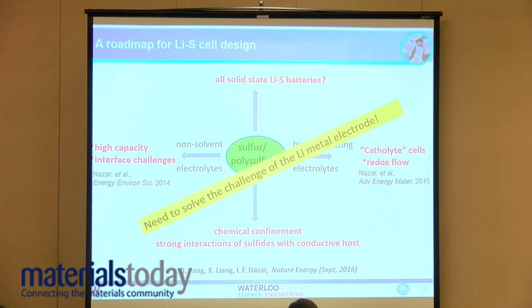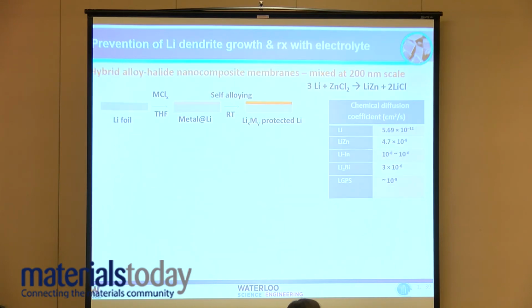So if we want to make sulfur cells function, we have to solve the challenge of the lithium metal electrode. And that means passivating or somehow forming a lithium ion conducting film at that negative electrode. So I explained that magnesium does not form dendrites. Well, lithium metal does, and it does so under circumstances where there is inhomogeneous current density at that interface. So our approach to this was to make some mixed alloy halide nanocomposite films from a very simple reaction, which is shown here. Simply, it's an in situ reaction.